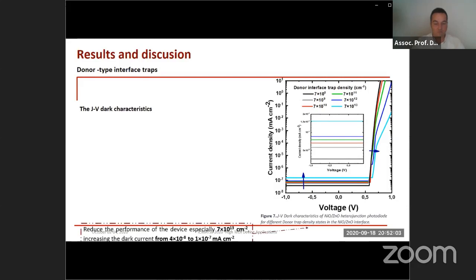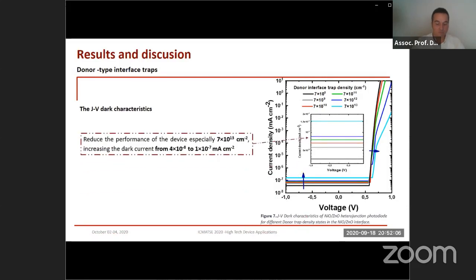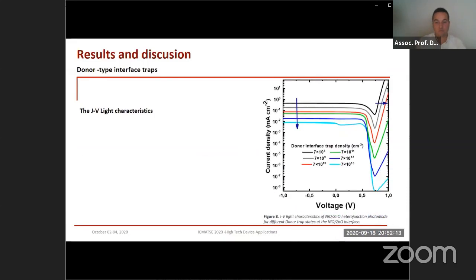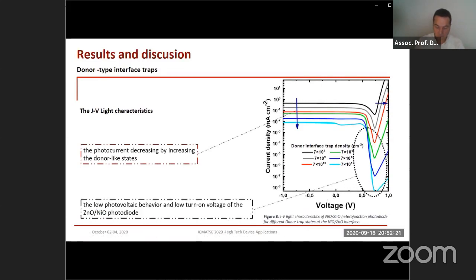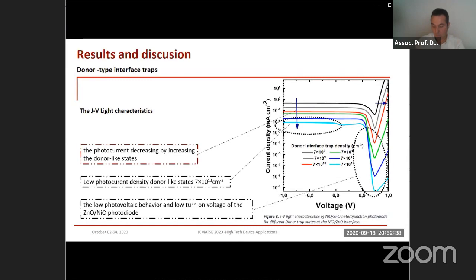In the absence of light, by increasing the donor traps, dark current rises, especially at higher trap density. If there is UV, the photocurrent density shows as follows. The light current is more affected by donor trap density. As we see, donor trap density is a powerful influencing factor which reduces the device performance at 10^13. Now I'd like to move into the influence of donor interface traps on responsivity.